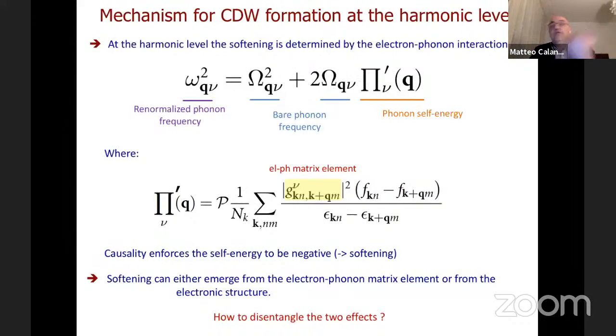So the softening that you have seen that leads to an instability both in bulk and single layer with HSE06 can emerge either from the matrix element or from the electronic structure. What we know is that when we apply this renormalization, the phonon frequency becomes imaginary, but we don't know what the origin is. Is it the electron-phonon matrix element, or is it the electronic structure?